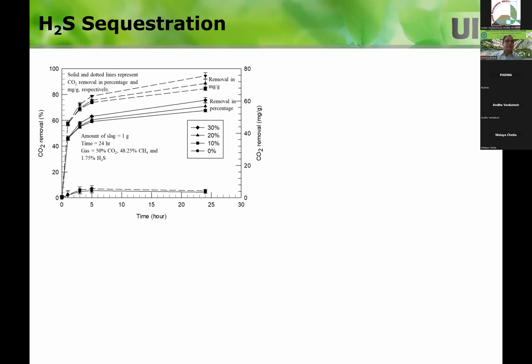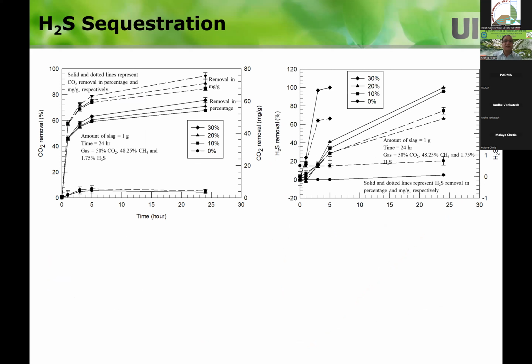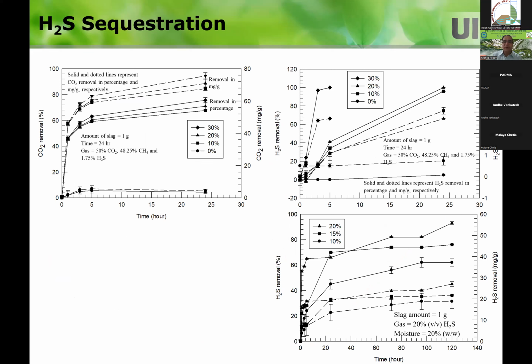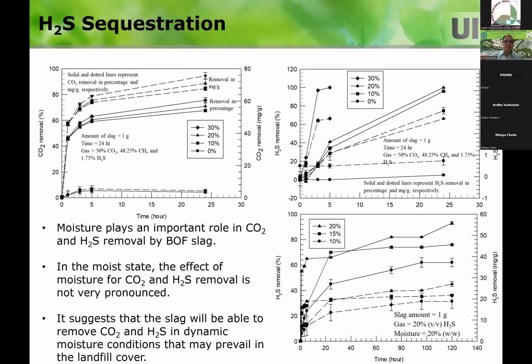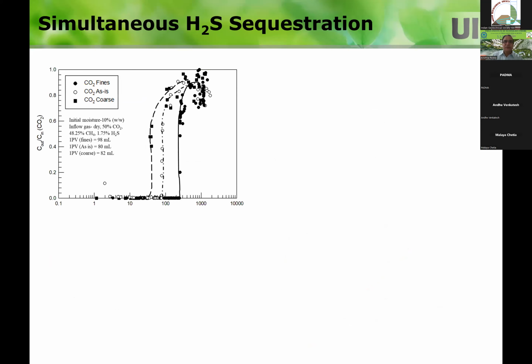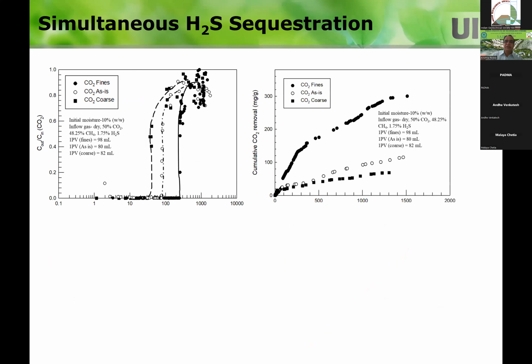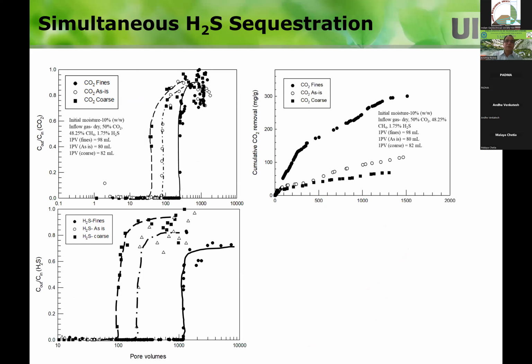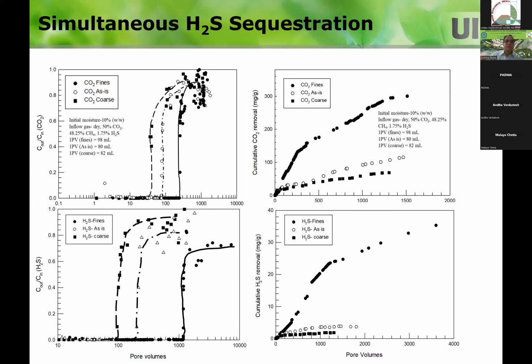So H2S sequestration is another important thing. Again, we put the slag and we put the H2S in there, and then see how much is getting removed. Again, we found that an extensive amount of H2S is removed by slag, which is very positive news for us. Our hypothesis is holding. Now, we looked at H2S alone, but also H2S in combination with CO2 and methane. So again, we show that CO2 is taken out and H2S is taken out. So both of them can be taken out at the same time. That's kind of the interesting thing.